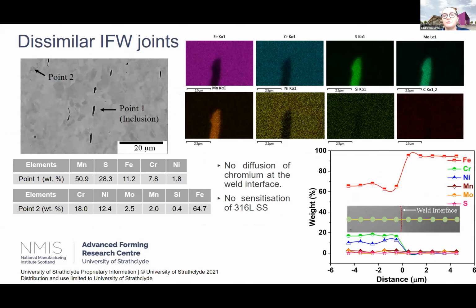We also wanted to keep in mind some of the issues with diffusion and creation of different carbides that can be issues within the current manufacturing route. And we wanted to check there was nothing nefarious within our microstructures. Looking at this, you can see that the only thing we managed to find in our EDS point map was manganese sulfide inclusions,